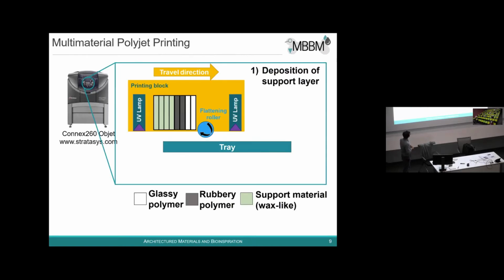So the first thing that I want to speak about is this three-dimensional printing. So we are using a commercial printer, and I will tell you a little bit later why we chose to go in this direction. So the printer is a polymer printer. It is based on the deposition of liquid monomer droplets, which are then flattened by a roller and cured by UV light.